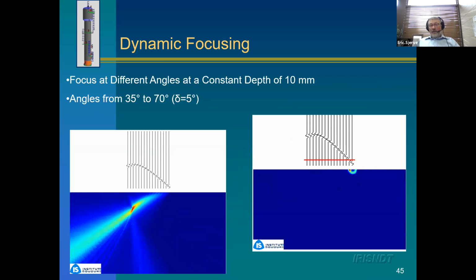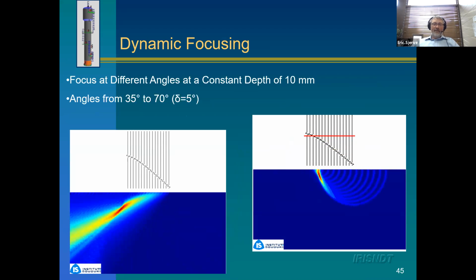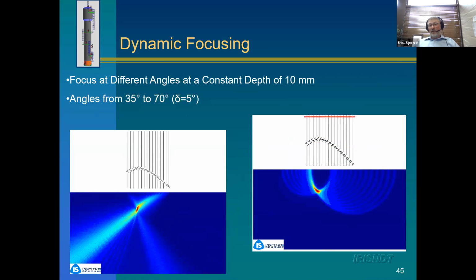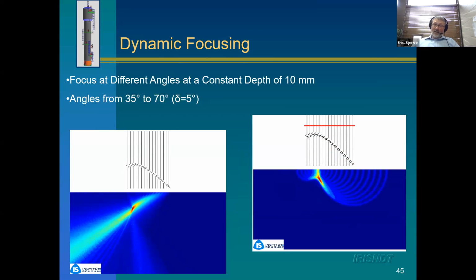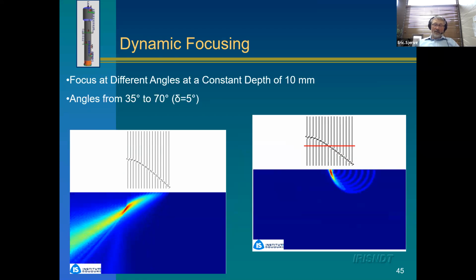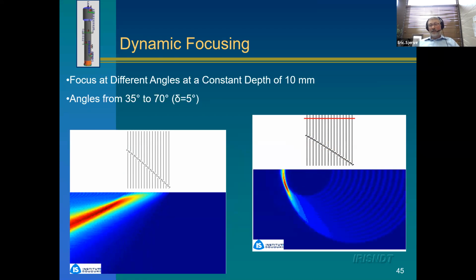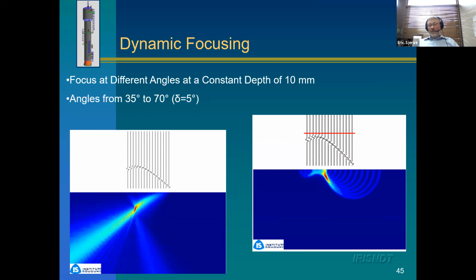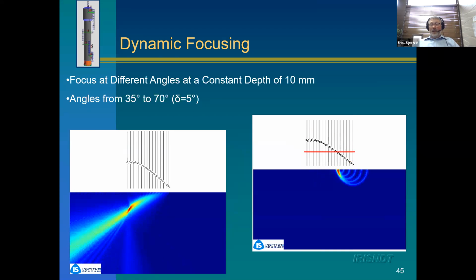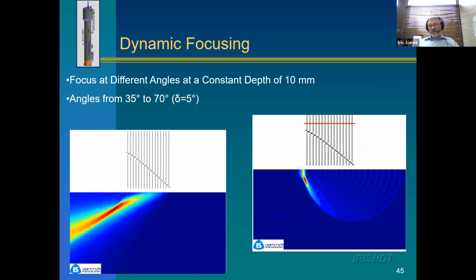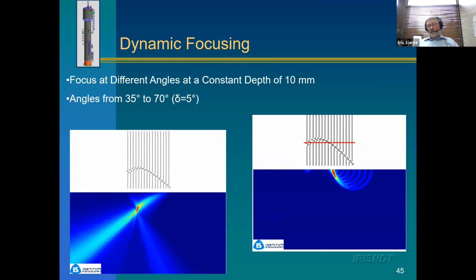And the real power of phased array is we can do all of it together. So we don't need to just move the sound beam and then do a second inspection where we have a different angle, and then a third inspection where we have a certain focal property. We can apply all that at the same time, and we can generate a sound beam that has a certain distance from the weld, a certain angle, and a certain focal property. And then we can generate another beam that might be a little different. And we can generate hundreds of these beams. So what we can really do is engineer the sound for the inspection that's being done. And that's really what we like phased array for: we can look at a component, figure out where there might be a defect or how we're going to inspect it, and we can generate a really nice inspection plan using the different sound beams to cover the whole area.